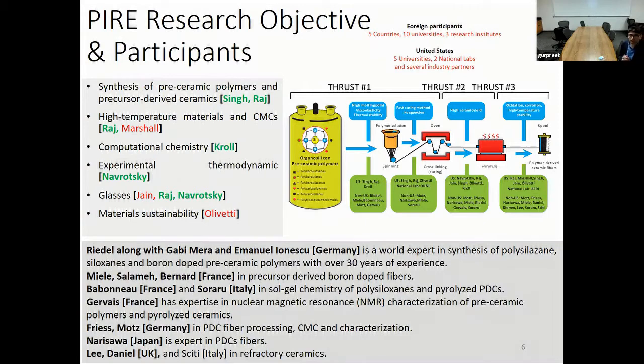And then we have research thrust area 2, which is focused on assessing the thermal stability of the spun fiber during the cross-linking and pyrolysis stages. So here we are involved in establishing, based on our spectroscopy analysis, the cross-linking mechanism or cross-linking pathways, polymer to ceramic yield, morphology of the fiber, chemical makeup of the fiber.